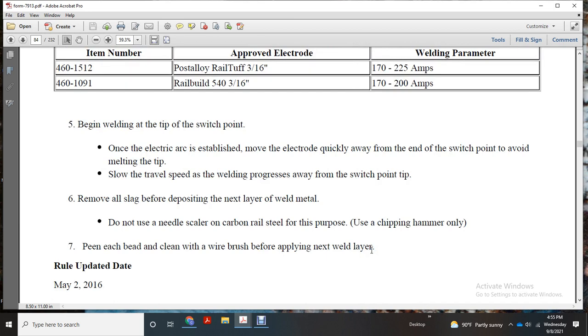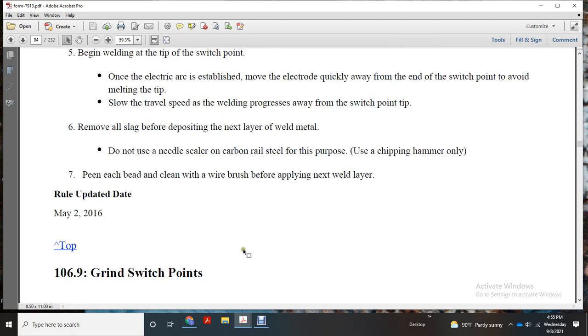Begin welding at the tip of the switch point. Once the electric arc is established, move the electrode quickly away from the end of the switch point to avoid melting the tip. Slow the travel speed as the welding progresses away from the switch point tip. Remove all slag before depositing the next layer of weld metal. Do not use a needle scaler on carbon rail steel for this purpose, use a chipping hammer only. Clean each bead with a wire brush before attempting the next weld layer.